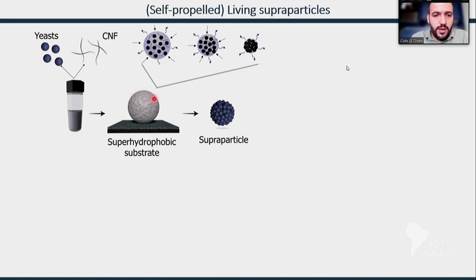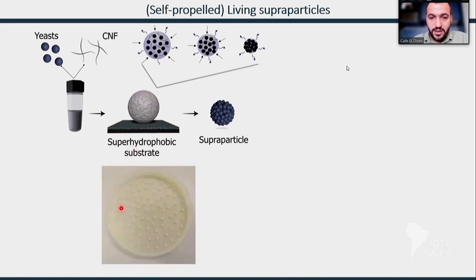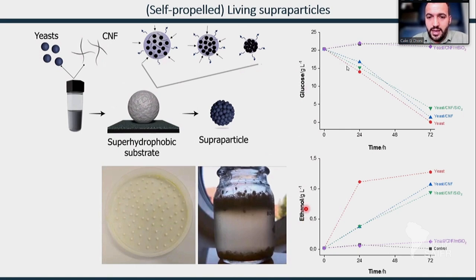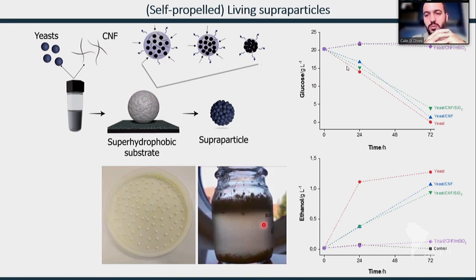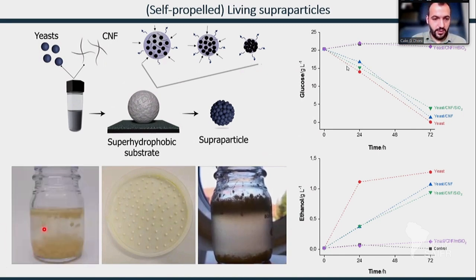Sorry. So we produced these round-shaped particles that are living; they are able to convert glucose into ethanol. You can see here, I hope you can see. As CO2 is also produced and its solubility in water is low, it sticks to the particle and increases the buoyancy. You can see the particles moving up. As they reach the interface with air, the solubility of CO2 is high, so they release the CO2 and again precipitate. So there is a vertical movement depending on the yeast activity in the particle.